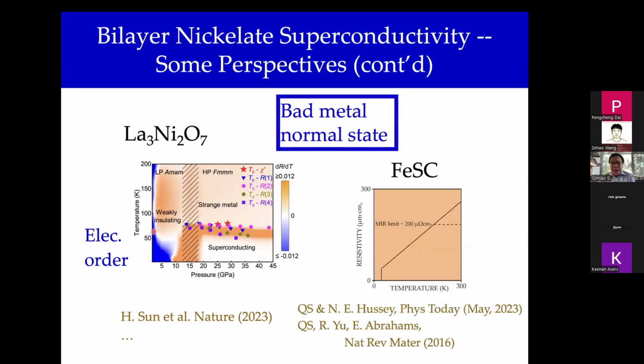In a slightly more specific fashion, and I'll talk more about this, the iron-based superconductors certainly have been extensively studied over the past decade and a half, slightly more than that. And one of the features that characterize iron-based superconductors is that if you look at the room temperature resistivity, it's reaching or surpassing the Mott-Ioffe-Regel limit. And so it is a bad metal, and that certainly is a feature also shared by these new